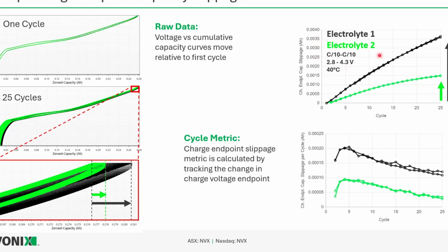So we can see here a quick example where two different electrolytes with pair cells here, so it's very consistent, have very different slippage rates. One is multiple times faster than the other. And this is telling us that there's a lot of electrolyte oxidation happening at the cathode, and that this electrolyte 1 is probably not the best for these conditions of higher temperatures and higher voltages in these cells.